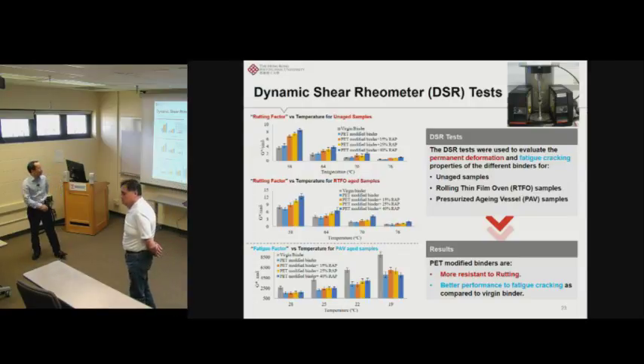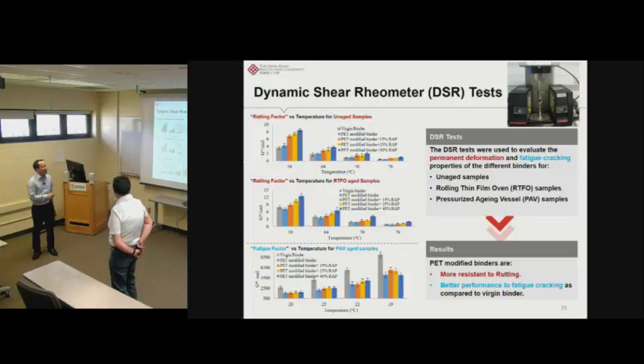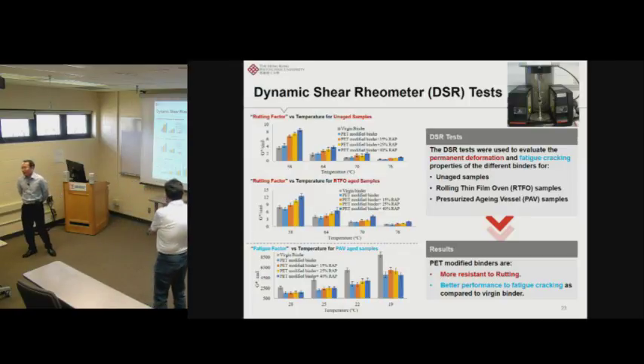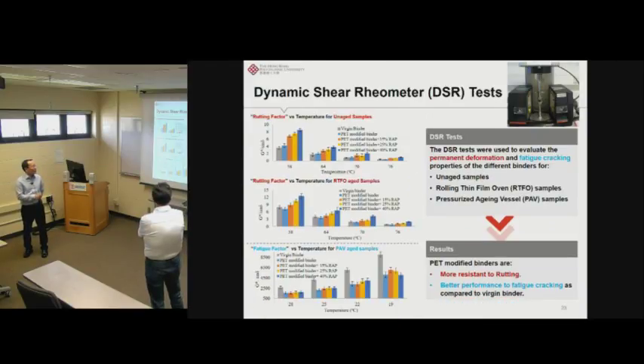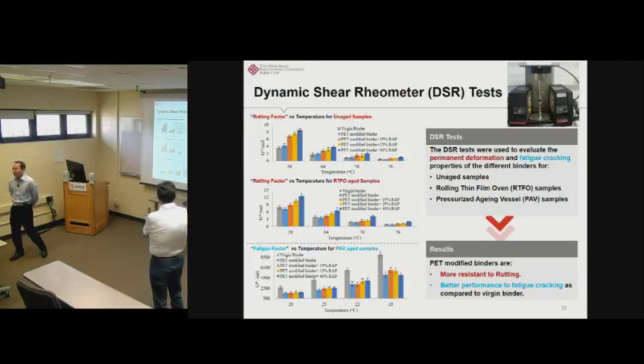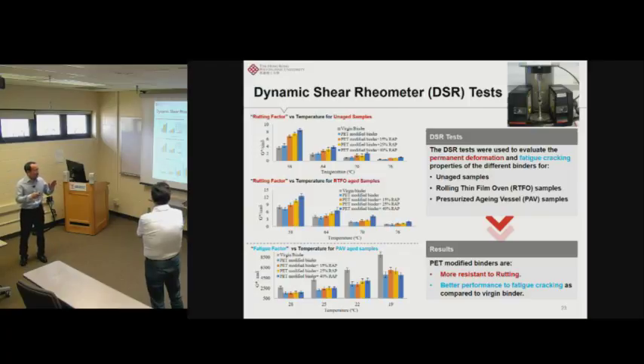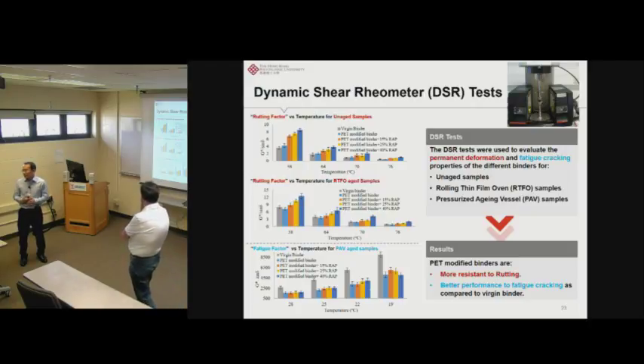So we simply compare the testing results, the G star and the phase angle. We simply check the values for the G star, whether it's increased or decreased. We didn't touch the threshold value. So we just present our results based on the rutting factor values. We didn't see it pass a certain threshold value or fail a certain threshold value.